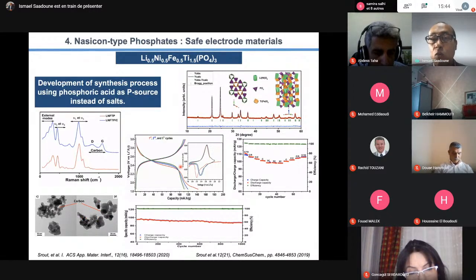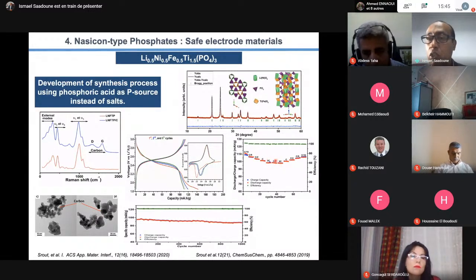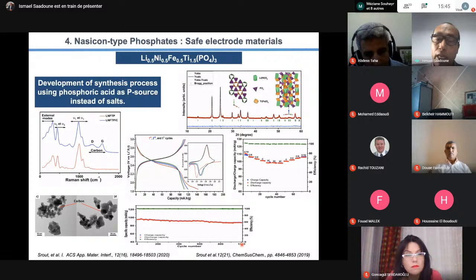And then we use this material in a half cell, and you see we have good reversibility of the charge and discharge process and good response at high rate. 5C means charging and discharging your battery in 12 minutes. But what we were surprised by is the long-term cycling, 1,000 cycles. Normally in the scientific setting, in the lab, we need only 50 cycles to prove the concept, but here we go until 1,000 cycles, almost the case of a practical, industrial battery.